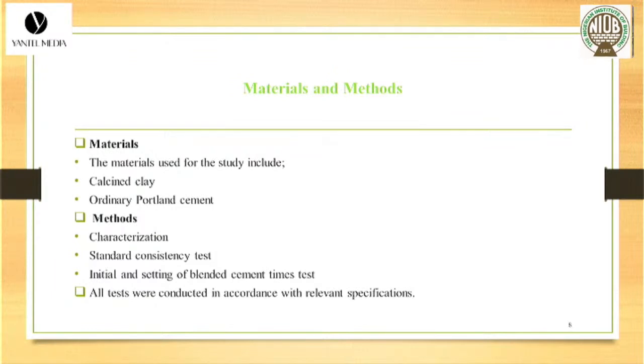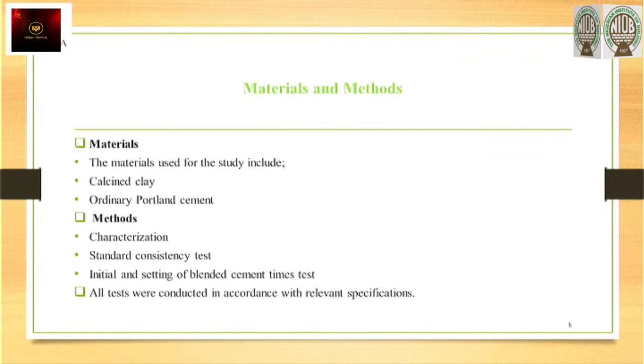So the materials and methods. The material used for the study is the calcined clay. The clay, first of all, was sourced from different sources, and a preliminary investigation was carried out on the clay samples to determine the clay that has the most adequate properties suitable for a pozzolanic material. After which, the clay was calcined at a temperature between 650 to 800 degrees centigrade. And the other material used was ordinary Portland cement. So the methods used were a characterization of the materials, then the test on the standard consistency, and a test on the initial and final setting time of the blended cement. All the tests were conducted in accordance with relevant specifications. The next slide, please.